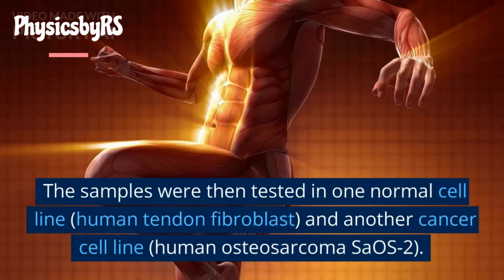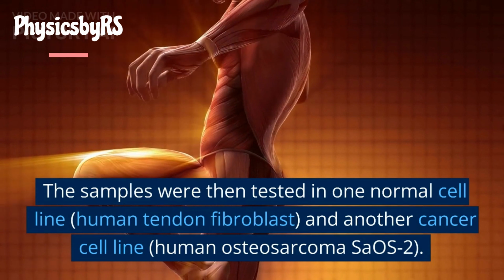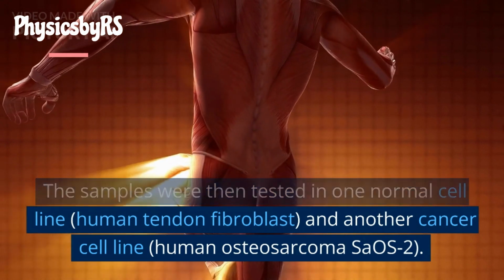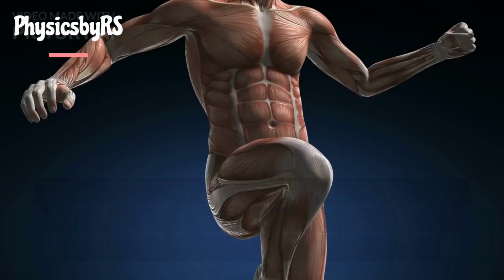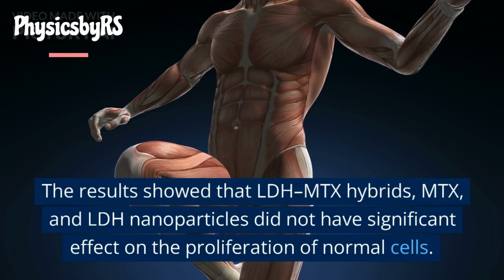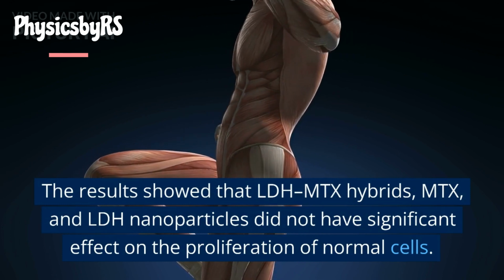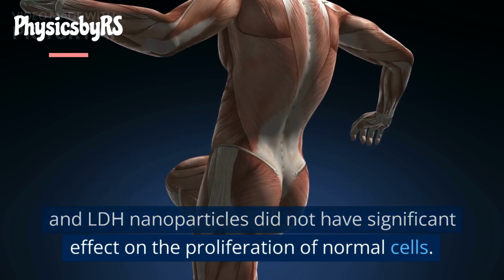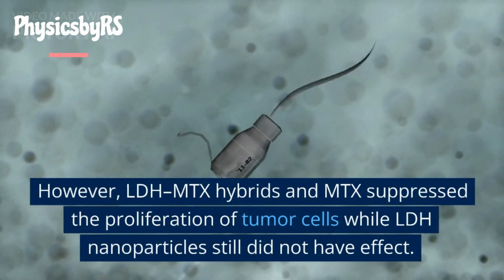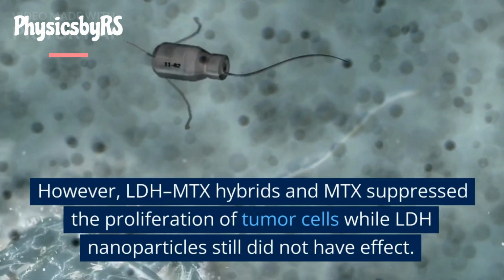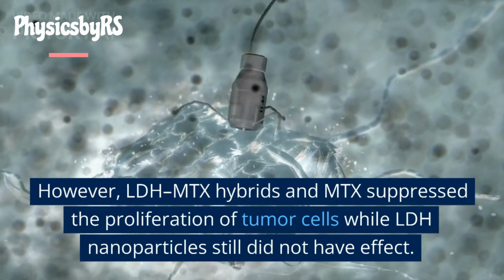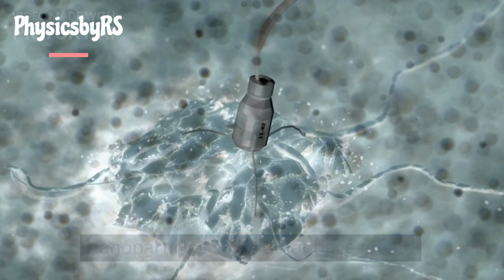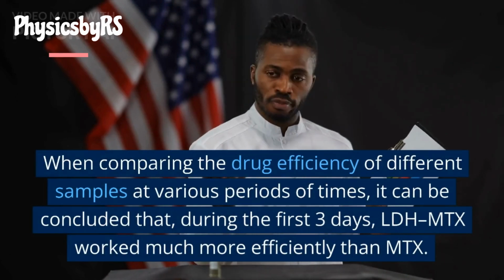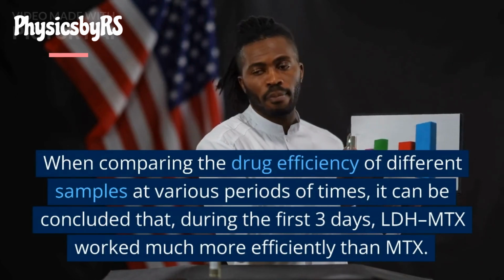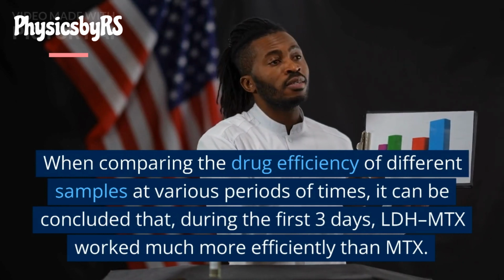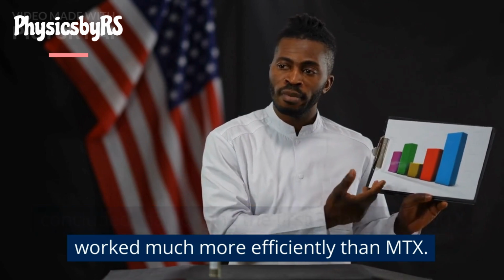The samples were then tested in one normal cell line, human tendon fibroblast, and another cancer cell line, human osteosarcoma SAOS2. The results showed that LDH-MTX hybrids, MTX, and LDH nanoparticles did not have significant effect on the proliferation of normal cells. However, LDH-MTX hybrids and MTX suppressed the proliferation of tumor cells while LDH nanoparticles still did not have effect. When comparing the drug efficiency of different samples at various periods of times, it can be concluded that, during the first 3 days, LDH-MTX worked much more efficiently than MTX.